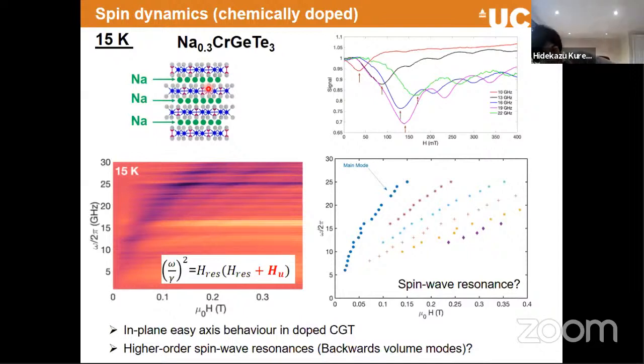I see. Okay, that's right. Thank you very much for the comment. Actually, we didn't investigate this critical behavior measured by the damping, and for this g tensor, g anisotropy by doping, we actually haven't investigated yet. Indeed, this is definitely an excellent suggestion, and we will definitely measure and then quantify it. One thing I noticed, also from your review paper, is that the gyromagnetic ratio is a good measure of the g factor. I don't have a clear answer of yes or no, but at least we can measure this g factor anisotropy by using the gyromagnetic ratio anisotropy, and then we will.